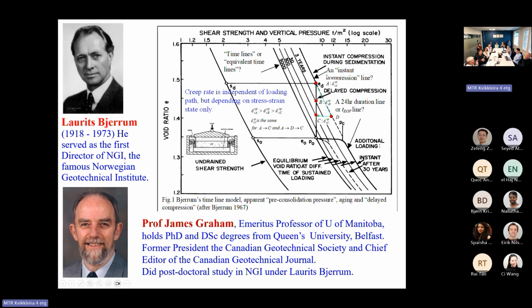You can see this model again. You can see the stress is constant. According to Maxwell model, when stress is constant, viscoplastic strain rate is constant. Actually not. When the time increases, the viscoplastic strain rate is getting smaller and smaller, even very, very small. So this rate gradually decreases, not constant.